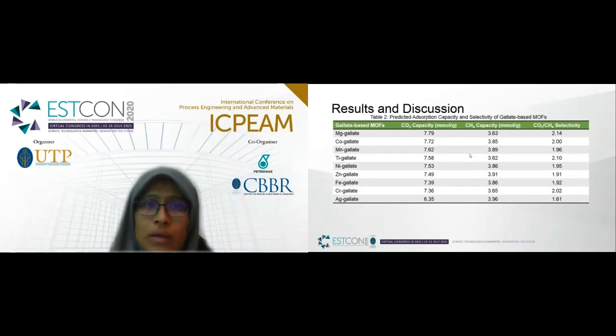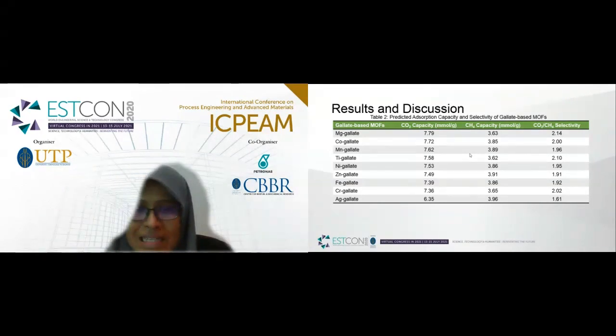Based on the predicted adsorption isotherms, adsorption capacity and selectivity of gallate-based MOFs at ambient conditions can be determined as shown in Table 2. The adsorption capacity is an important parameter in evaluating the MOF for CO2 adsorption. However, this approach cannot estimate the binary gas adsorption because it is not considering the competitive adsorption among the different components in a gas mixture. As we can see, all the capacity values for CO2 are higher than CH4.